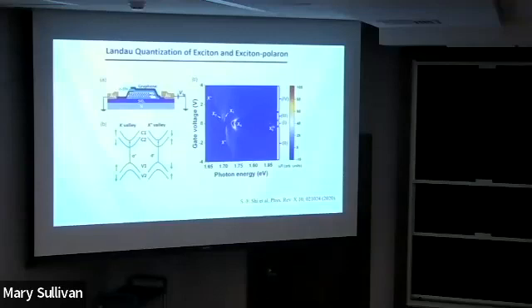We did a very nice experiment which we never published. How do you screen a material most dramatically? Put it on the metal. We actually did that. The absorption does not change that much, within tens of meV, like 10 meV, 20 meV, but not that much.